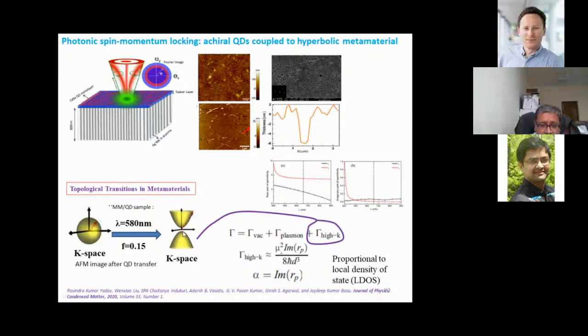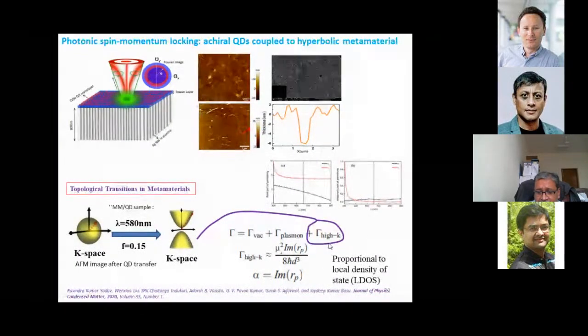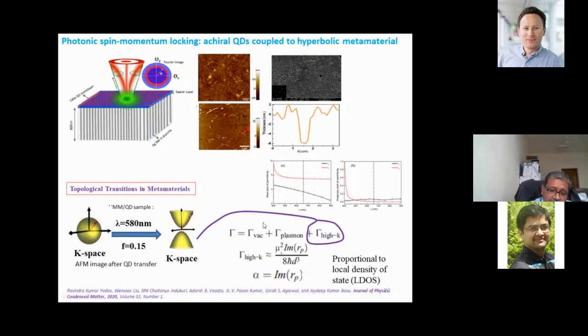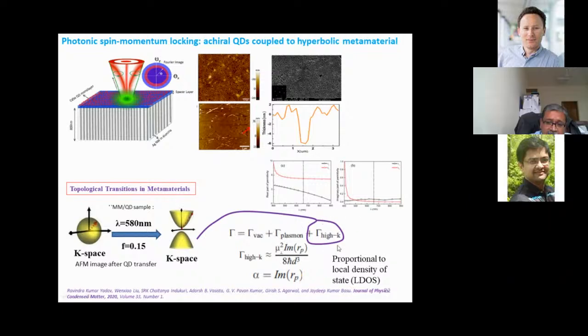Remember that the hyperbolic dispersion has these large k modes which emerge. So you have these high k modes in addition to the normal vacuum modes, and the normal plasmon mode, since these are based on metals. But you also have this high k mode, which comes because of the emergence of this hyperbolic phase that happens around a certain wavelength.